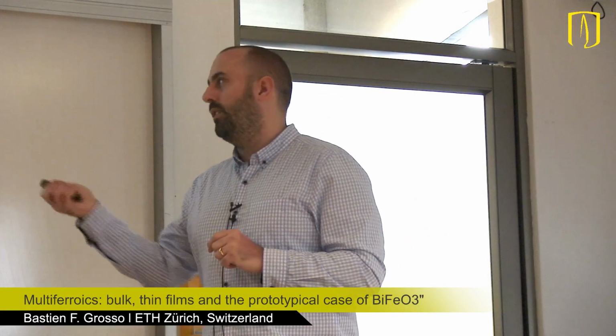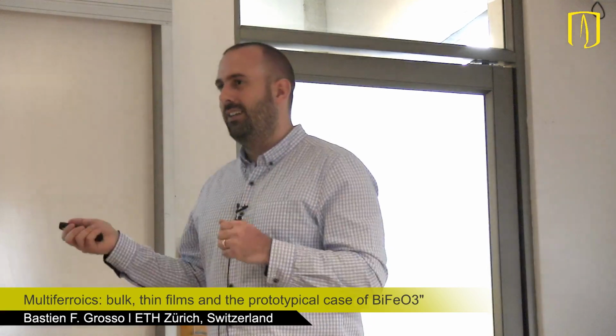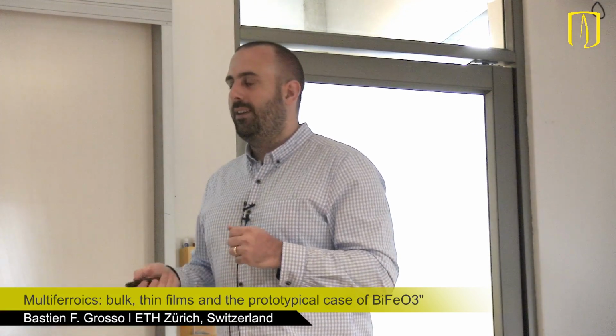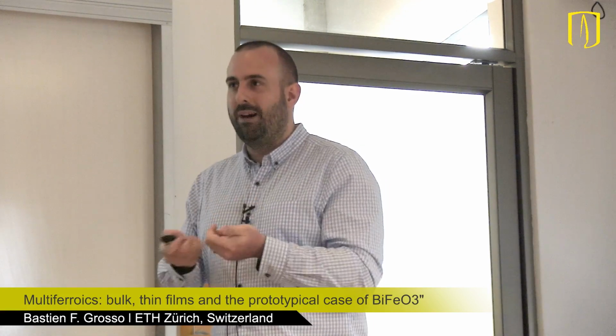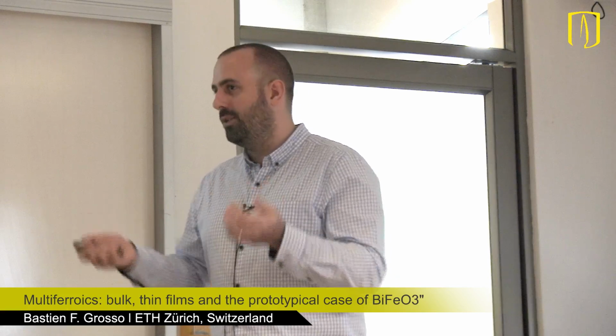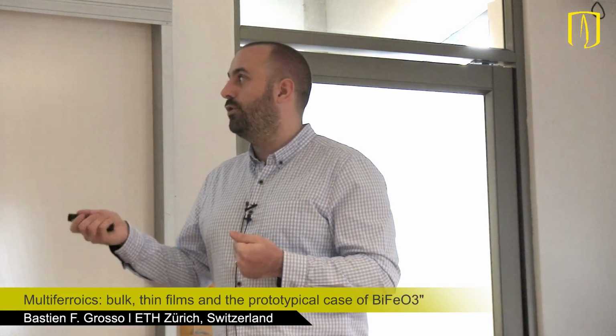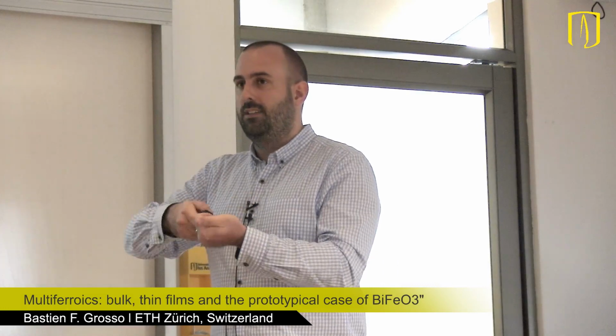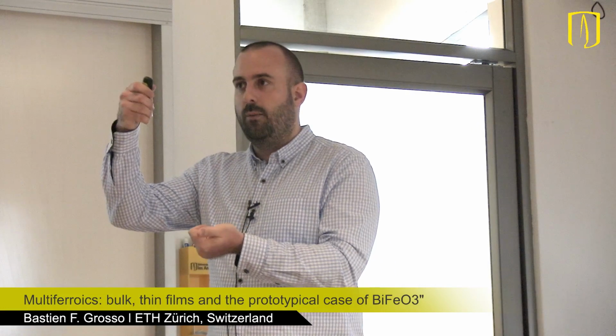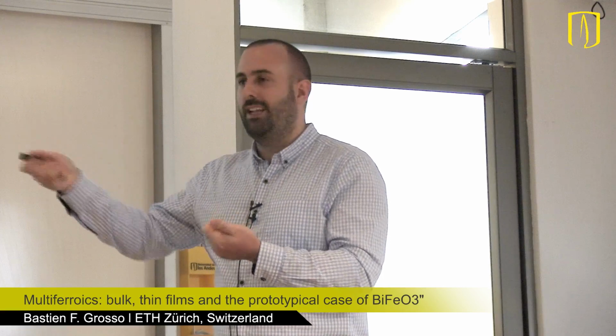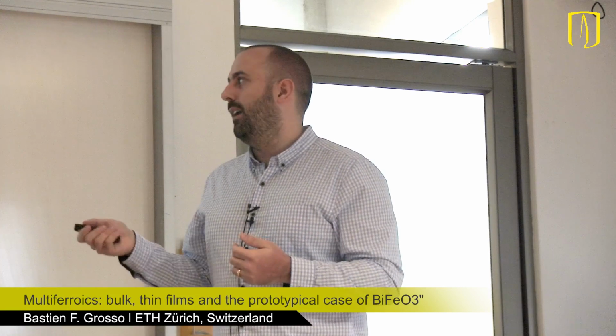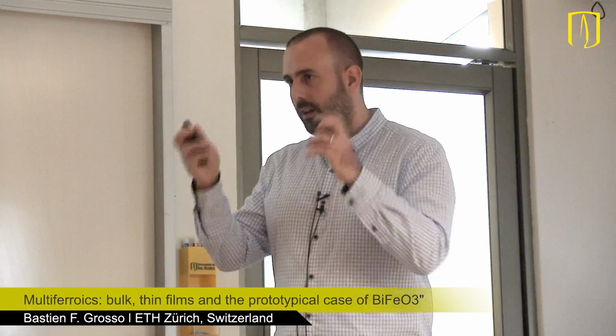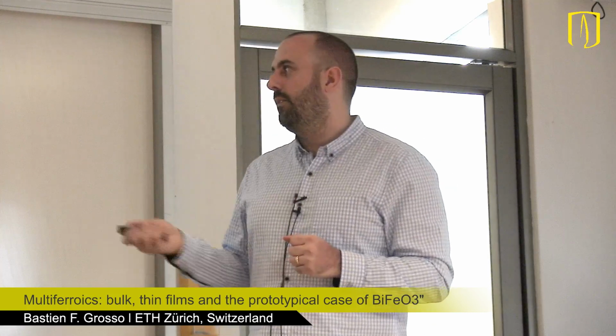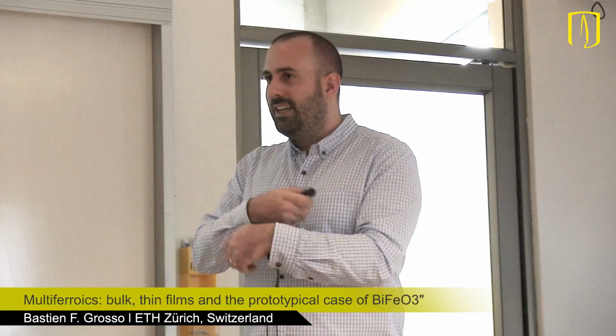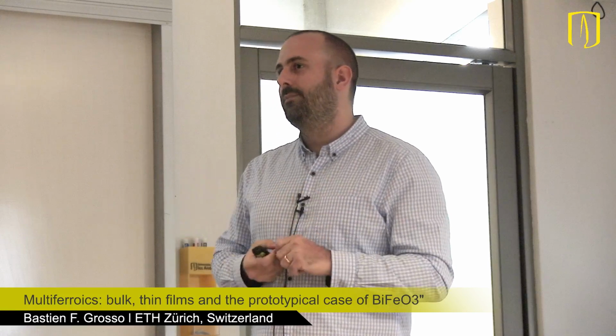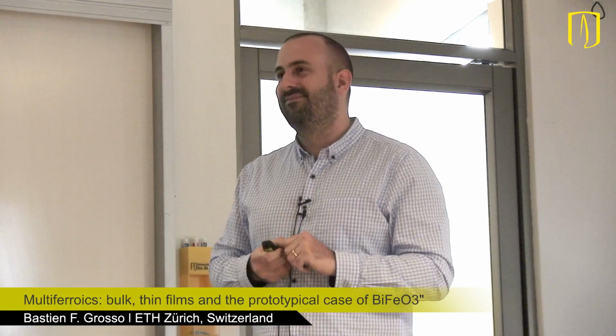So, yeah. But let's say for different application, out of bismuth ferrite, to try this same strategy, there are different ingredients that should match. And I think they're maybe not so easy to find, because the first one should be that you should find a phase that is not too high energy above the ground state. Otherwise, the electrostatic would be lower than this. And that's maybe one big ingredient that is important to find. And probably bismuth ferrite is one of the easiest to distort structure. But yeah.